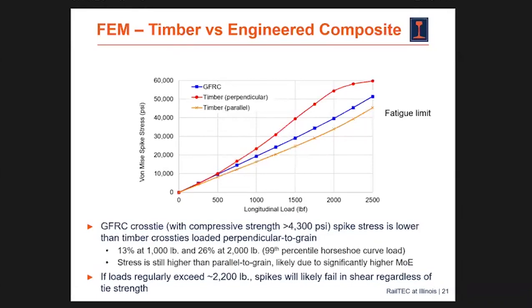And so how does this again compare to timber? We're trying to hone in on a specific compressive strength, a specific modulus of elasticity, but if you can come up with your perfect idealized composite tie, how does it still compare to timber? And we'll have GFRC in blue compared to timber, perpendicular in red, and parallel in orange. And at a high level, we see that there is certainly a benefit to the composite tie over timber perpendicular to grain, but it's still not quite as good as that parallel to grain. And it's because of that lower modulus.